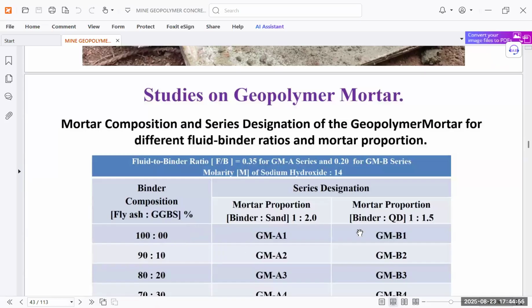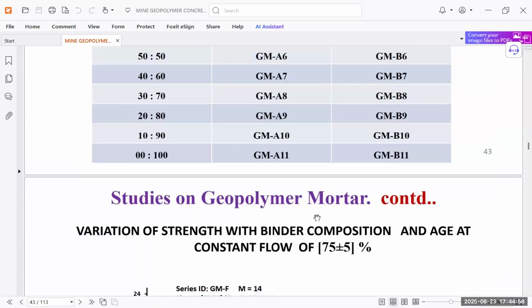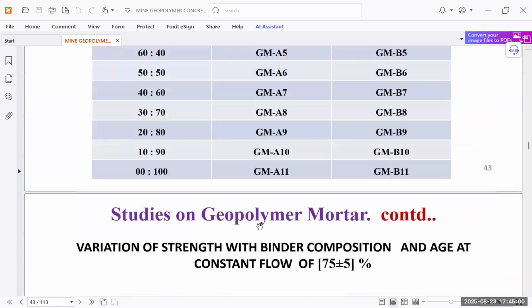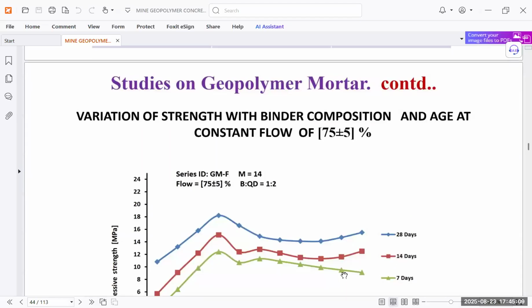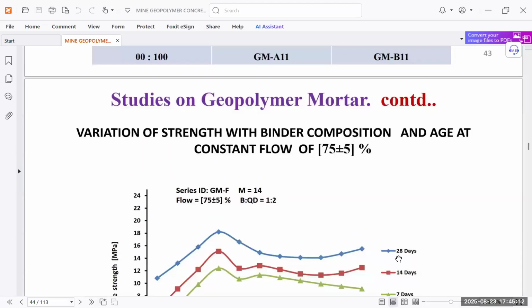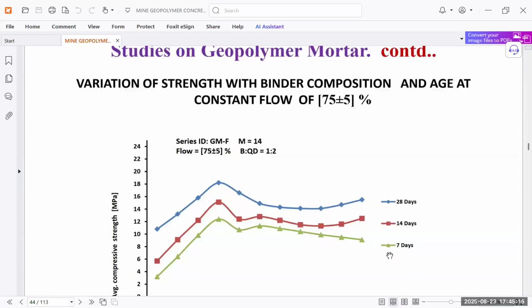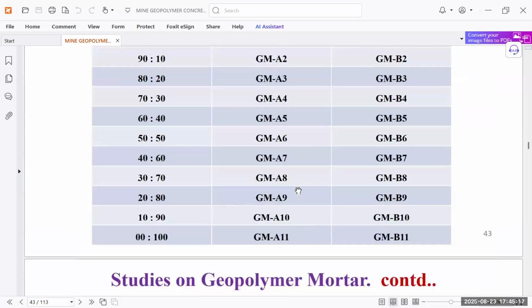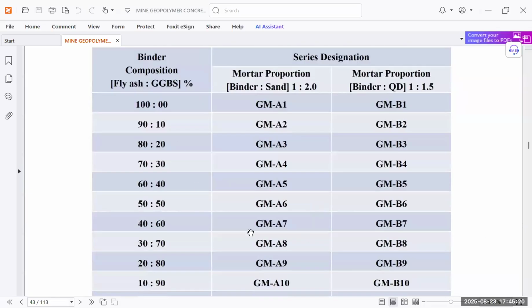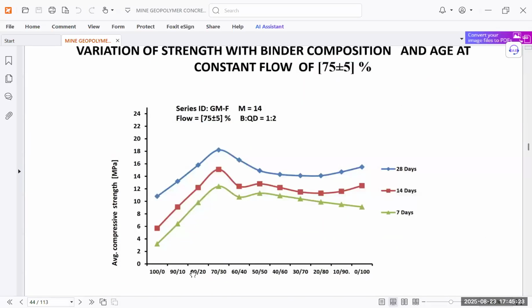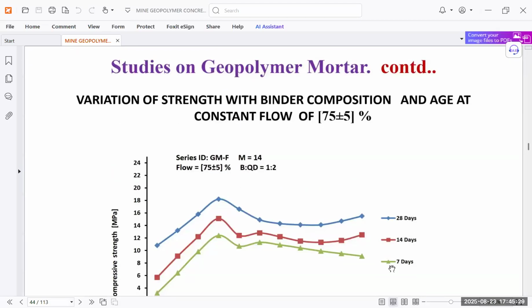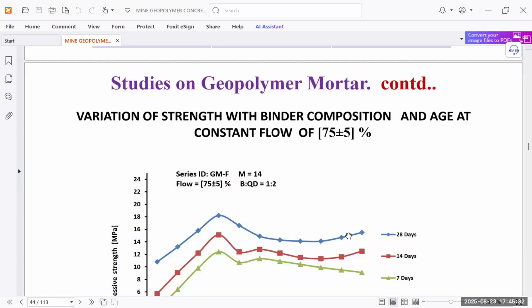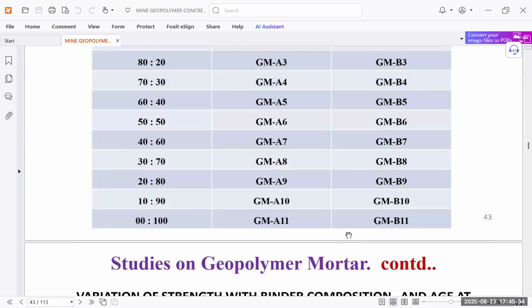Then we made some definitions and plotted the studies in this graph. Studies on geopolymer mortar show the variation of strength with binder composition and age at a constant flow of 75 plus or minus 5%. This is the graph we obtained, showing the 28 day, 14 day and 7 day strength. We plotted this series, GMA up to GMA11, in this graph. We can see how the ratio changes the compressive strength at 28 days, 14 days and 7 days. This is how we get the strength for the different geopolymer ratios.